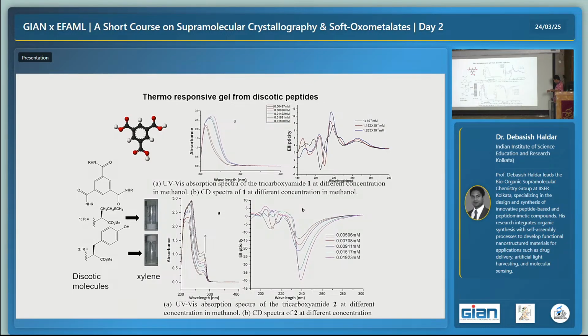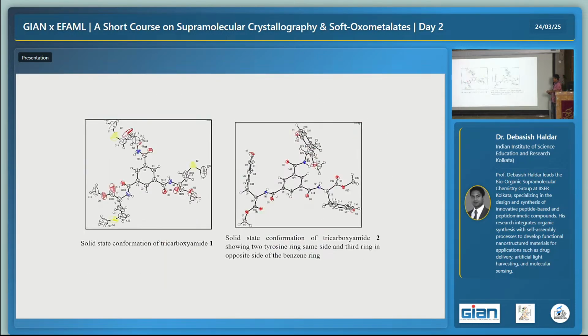From solution study we figured out that the compounds self-assemble in different manners. When it is methionine, it has something different than tyrosine. Then we got the crystal structure. From the crystal structure it appeared that when it is methionine, the C3 symmetry is still present. But when it is tyrosine, due to large hydrophobic interaction, two of the tyrosines might be on one side of the central benzene ring, and another tyrosine is on the opposite side. That means theoretically the compound is C3 symmetric, but practically you lose the C3 symmetry. The compound is not C3 symmetric in the crystalline state anymore.